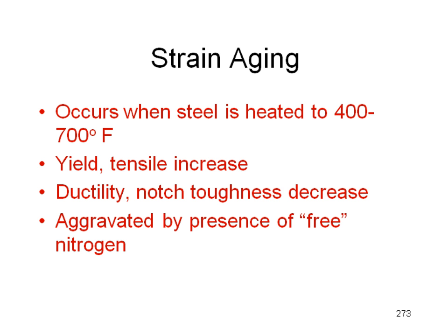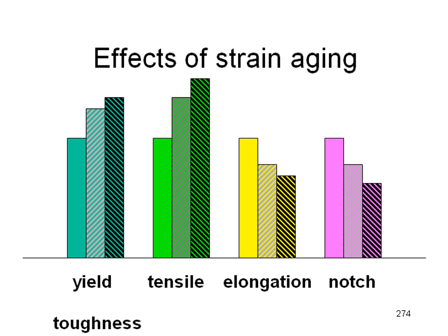Now, with that increase in yield and tensile, we need to be concerned about the properties of the steel we're welding on. In addition to what the cold working is doing, we have this phenomenon called strain aging. And strain aging occurs when we heat steel between 400 and 700 degrees F. The yield and tensile further increase, the ductility and the notch toughness further decrease. So again, our hot rolled properties, our cold worked properties, and now the strain aged properties. And I'm concerned again about the loss of elongation and the notch toughness.